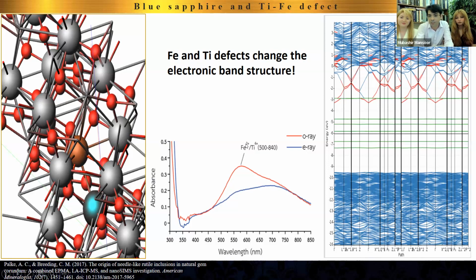Okay, so the iron being in 2+ and titanium in 4+ charge states create this beautiful hump of about 570 nanometers in the UV spectra that creates the blue color. Because consider this, over here on the 700, 600 nanometer side, especially this side, we have the red colors that are being absorbed. Over here, we have the greenish ones that are being absorbed. And all that is left, this transmission window, is in the blue range. So we have the blue color that arises from the iron and titanium incorporation in the sapphire structure.